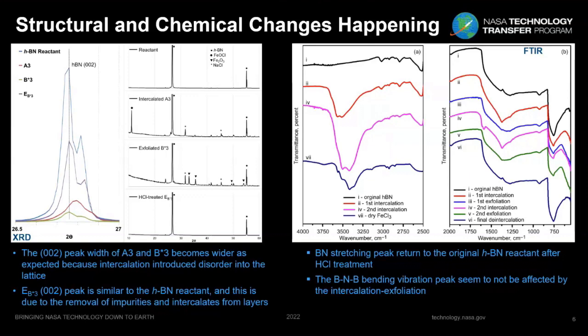And if at the end you use hydrochloric acid to clean the sample, you obtain an exfoliated sample with a clean 002 peak that is back to normal again. This normal peak is smaller than the original one, but still the same kind of peak. And the full spectra show a totally clean spectrum, without any iron species anymore.